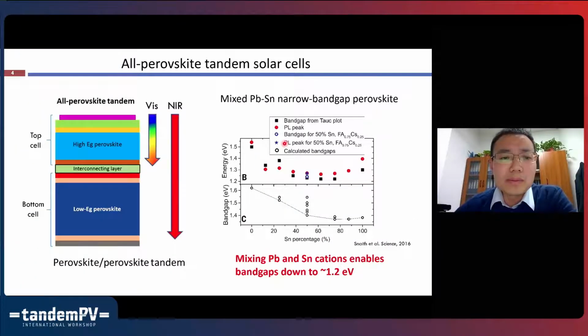A very important component of perovskite-perovskite tandem devices is the low band gap perovskite subcell. Many speakers talked about the wide band gap perovskite yesterday, and this field has also achieved very rapid progress in the past few years. For narrow band gap perovskite solar cells, we usually have to mix a certain amount of tin into the lead-based perovskite, and when the tin content ratio is around 50 to 60%, we can achieve the lowest band gap, currently around 1.2 electron volts.